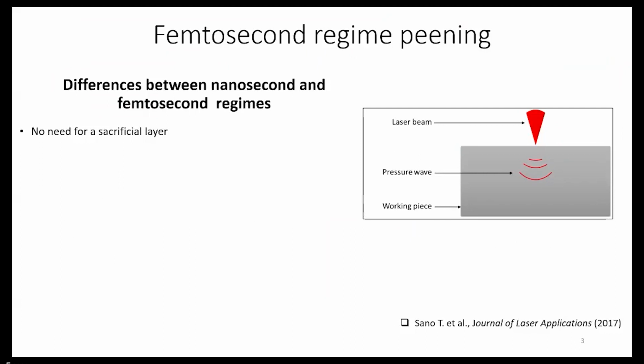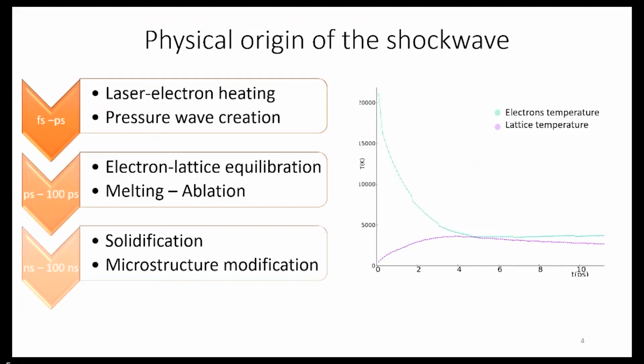The specificity of this work is to reproduce this with femtosecond lasers, because it has been shown by Sano that this technique doesn't need any sacrificial layer, which will allow other applications. Why doesn't it need any sacrificial layer? Because the origin of the shockwave is not the same. During femtosecond laser peening, the laser only interacts with the electrons of the material, which creates a high disequilibrium between the electronic temperature and the lattice temperature, which we can see here in the graph, and which creates the propagation of the shock wave without any sacrificial layer.